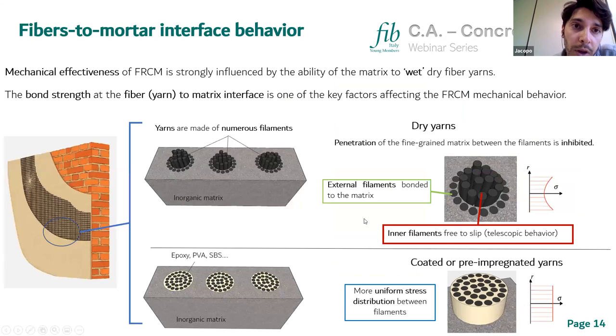And now I will show you what is, in my opinion, the most important thing on FRCM systems. And that is the fact that the mechanical effectiveness of FRCM is strongly dependent on the ability of the matrix to wet the dry fiber yarns. So of course, the bond strength that develops at the interface between the yarn and the mortar is a key factor, and the mechanical behavior of the composite is strongly dependent, of course, on the bond between the yarn and the mortar.